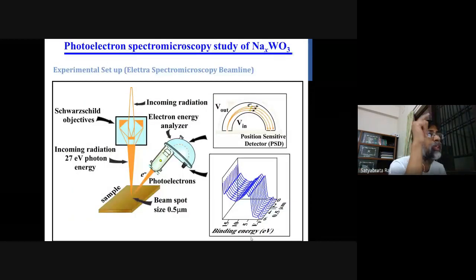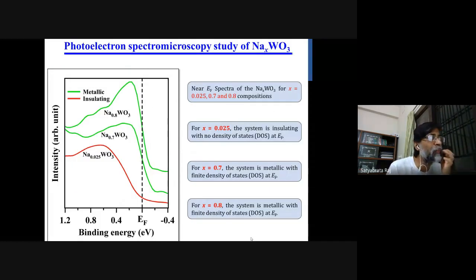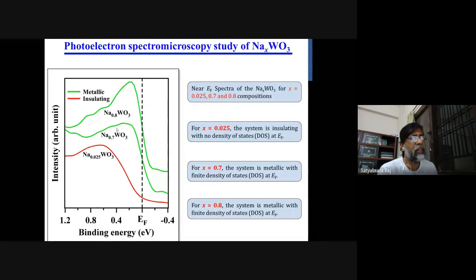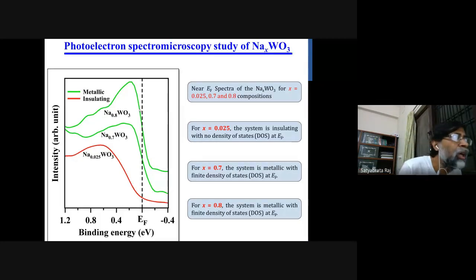So with this, we want to focus our studies, and we have taken 3 samples. One is a very lightly doped WO3, and 0.7 and 0.8 are the very metallic compositions. The systems with 0.8 and 0.7 should give a high density of states at the Fermi energy because they are metallic, whereas the low doping sodium WO3 is insulating and should give a 0 density of states at the EF. But if the percolation theory is right, then at some part you'll see a 0 density of states in a spectrum in the same sample, whereas at some positions it can be a metallic spectrum. So let's see what it says.